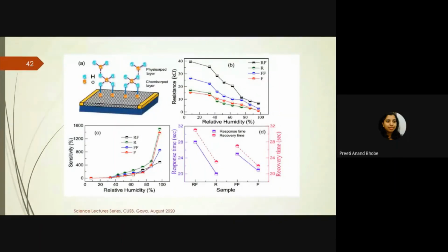We found that if we make a deposition of those rods or flakes or flowers on a glass substrate, then we see that its sensitivity to humidity is having a dependence upon the type of morphology it has. So rod flowers were having a particular morphology and they were showing a particular resistivity change with the humidity. Likewise, rods and flowers and flakes, the same SnSe made in different morphology, was showing us a change in its resistance and hence could be used as a gas sensor.